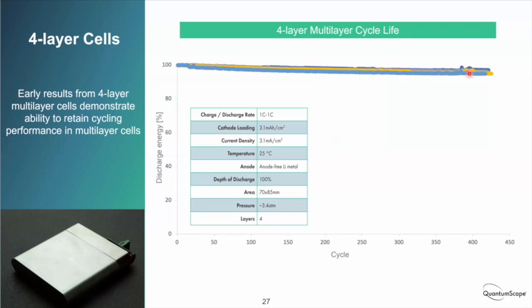They're passing 450 cycles as we speak, still going, retaining a lot of their capacity. Again, at 1C rates with the same cathode loading, room temperature, full depth of discharge, full commercially relevant area here, four layer cells. So it shows that there's nothing fundamentally impossible about doing multi-layering in our technology. And so then very recently, we went beyond four layers.